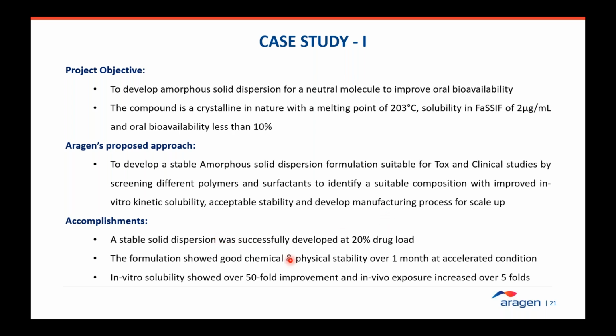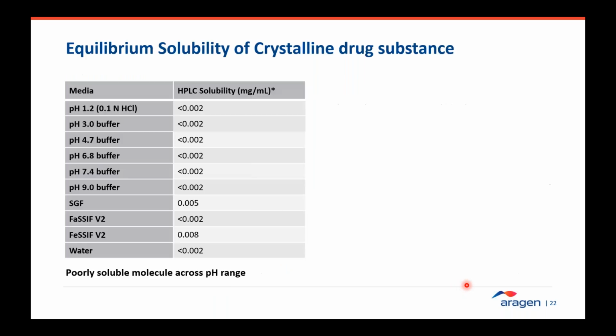So a stable solid dispersion was successfully developed at 20% drug load, and the formulation showed good chemical and physical stability over 1 month at accelerated condition, and the in vitro solubility showed over 50-fold improvement, which doesn't exactly lead to that many fold in the in vivo, but usually the solubility shows much higher improvement than the in vivo. And the in vivo exposure in the dog PK increased over 5 folds compared to the crystalline micronized suspension.